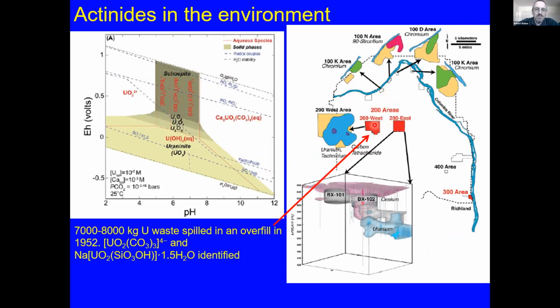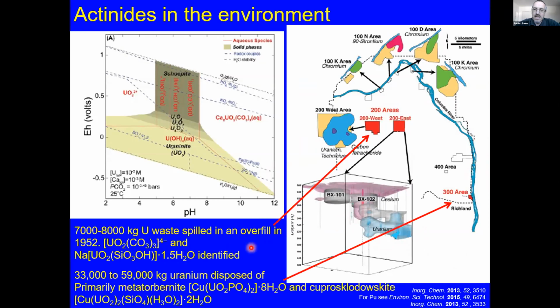So in this area, for example, somewhere between 7,000 and 8,000 kilos of uranium waste was spilt in one overfill event in the 1950s. So this waste was stored in single-shell tanks that are buried underground. Record keeping wasn't quite so good, so they still have no idea how much was spilt. And this is now going close to the vadose zone of the Columbia River. But using some X-ray spectroscopy, it's been shown that uranyl carbonates and uranyl silicates are the speciation controls here.